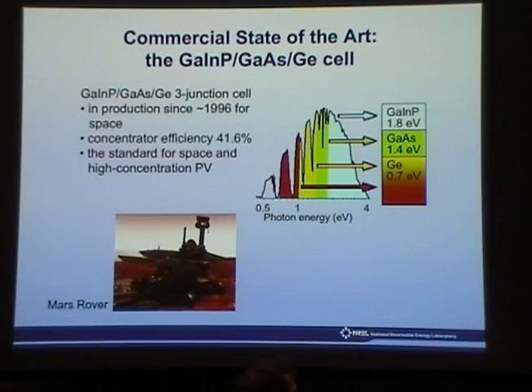So in terms of binning, we start with a germanium cell on the bottom. It's 0.7 eV. And it picks off these bottom 2 bins here. And then this gallium arsenide cell in the middle, 1.4 eV. And then it's topped by a gallium indium phosphide, about equal portions gallium and indium.